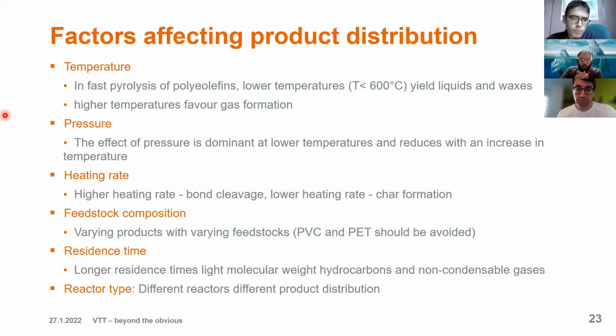because then your oil will be contaminated with halogens, with chlorine, or your oil will be acidic, which is of no value for future use. So these two types of polymers should be avoided. Residence time also has a very important role in pyrolysis. In reactors with longer residence time, you get lighter molecules, lower weight hydrocarbons, and non-condensable gases. And in short residence time, you get the opposite of that.